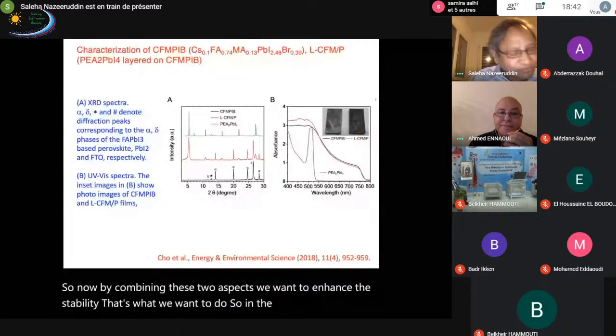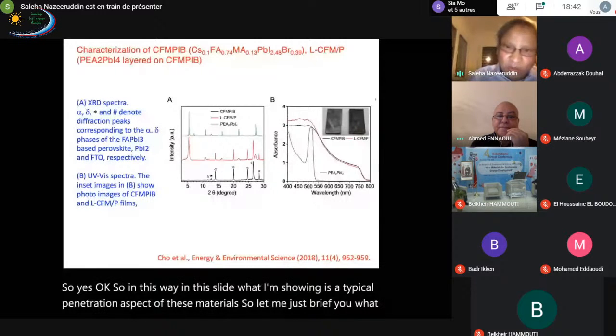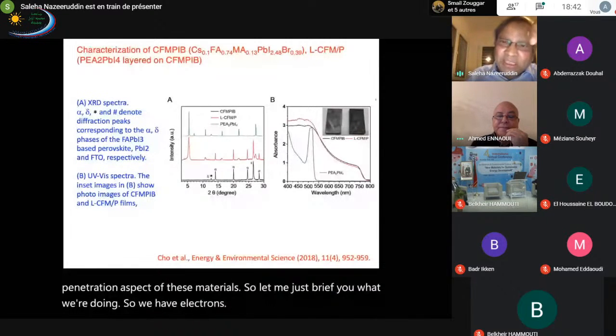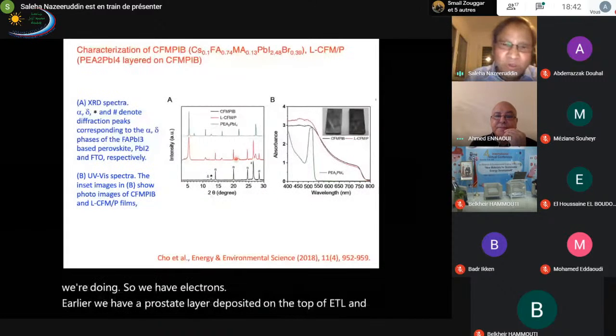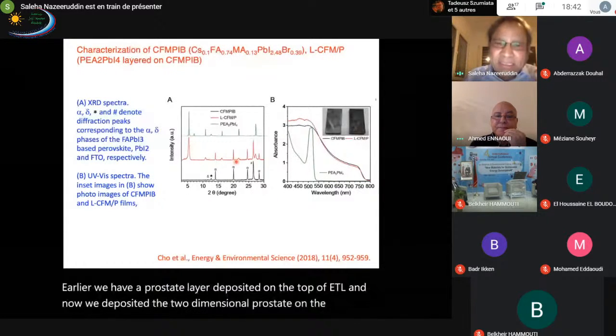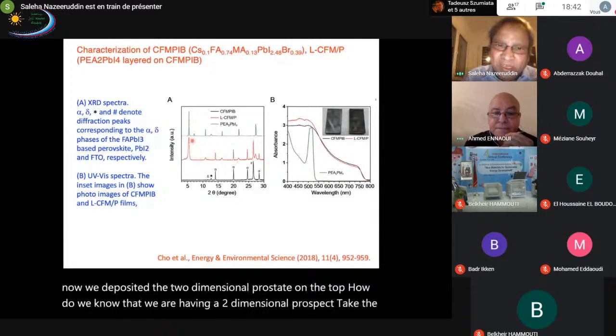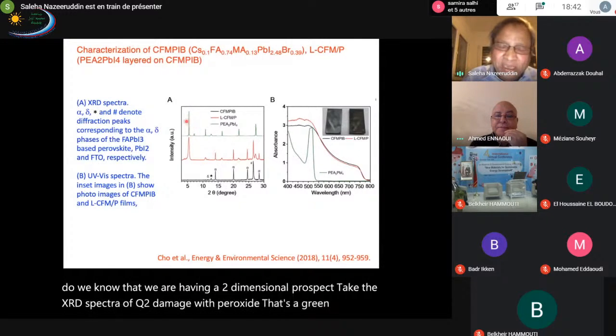In this slide, what I'm showing is a typical characterization of these materials. Let me just brief you on what we are doing. We have an electron transport layer, we have a perovskite layer deposited on top of the ETL, and now we deposit the two-dimensional perovskite on top. How do we know that we have a two-dimensional perovskite? Take the XRD spectra of pure two-dimensional perovskite, that's the green line, and this particular peak around 5 is a fingerprint for the two-dimensional perovskite. On the bottom, we have a peak at 11.5. This is a characteristic peak for the three-dimensional perovskite.